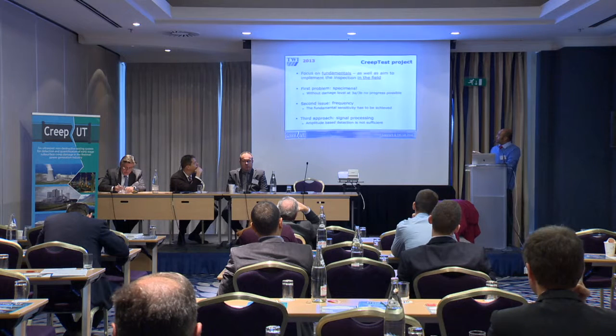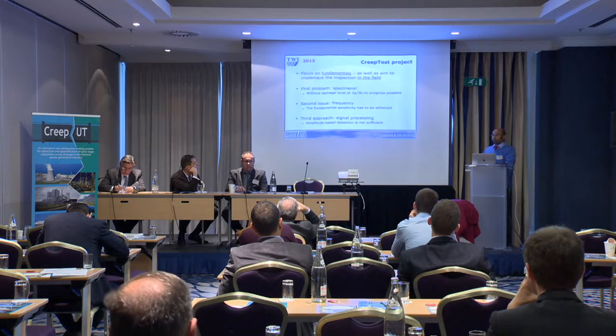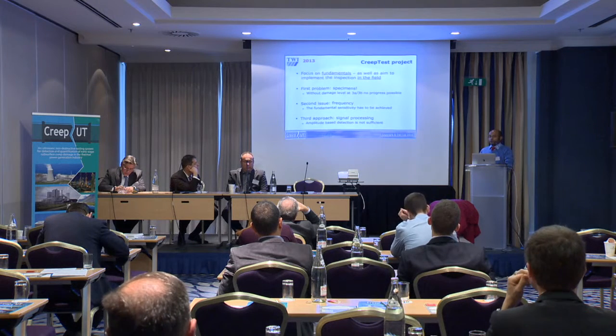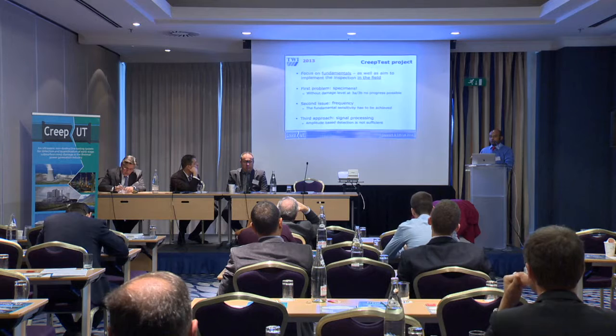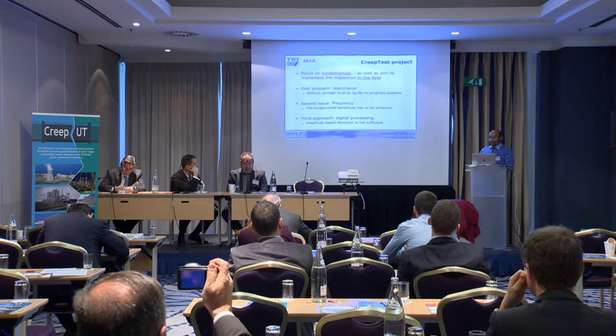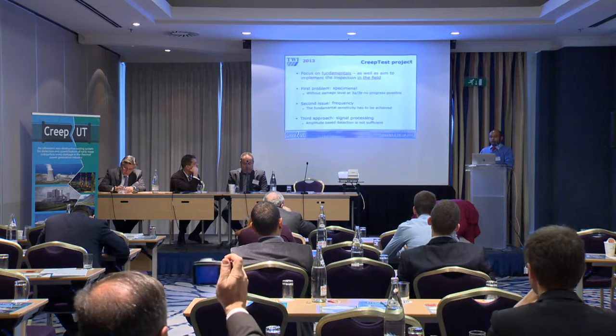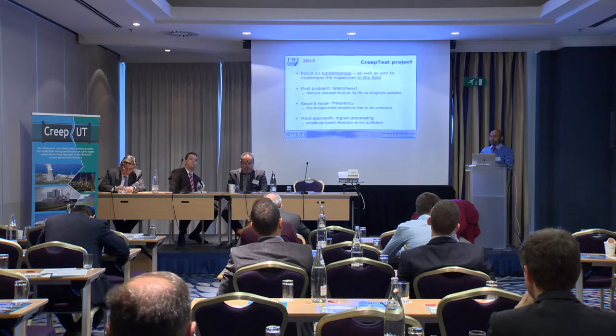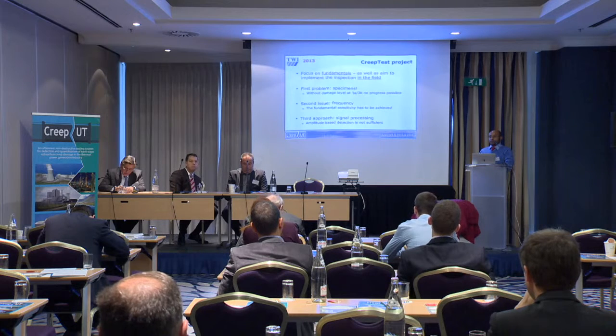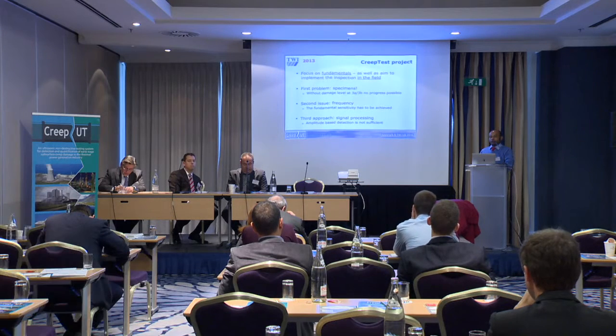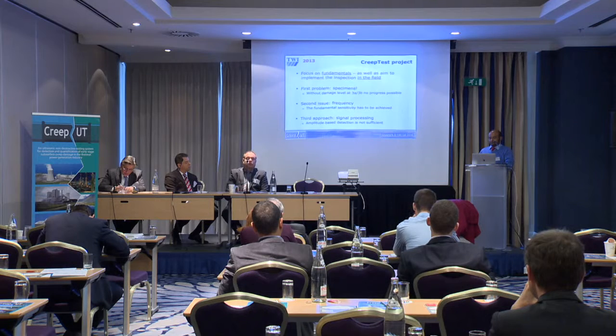Now we'll talk about specimens later. The other one was frequency, because frequency has a lot of effect, as Marco said, on the fundamental resolution, the temporal resolution for the damage. But also it has a lot of influence on the practical implementation side, because the higher the frequency, the more sensitive it becomes to the surface condition of your component, even before you get a chance to look at what is underneath the surface. So we knew that we were going to have a challenge with frequency.